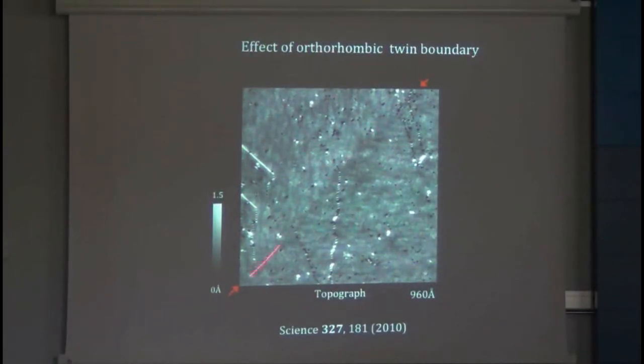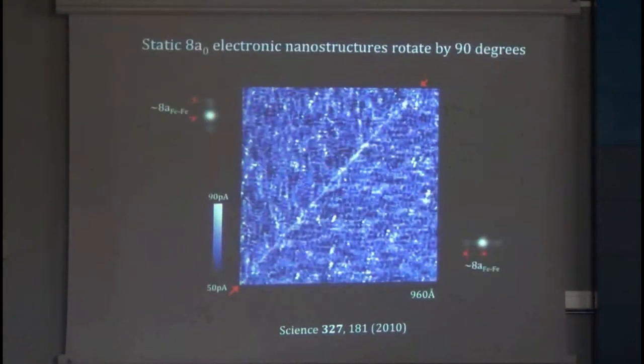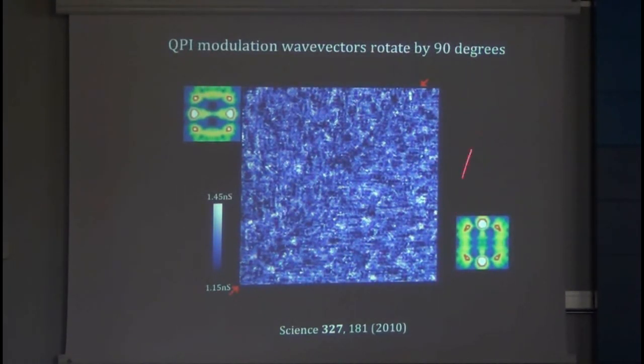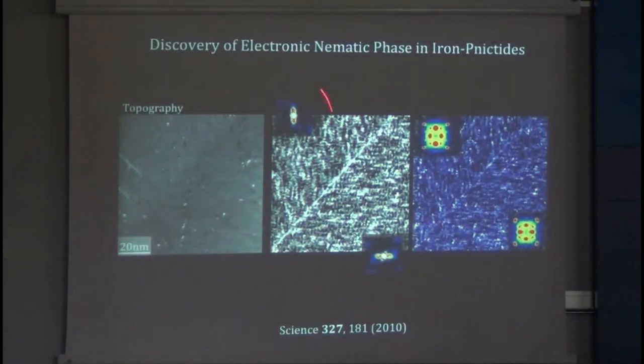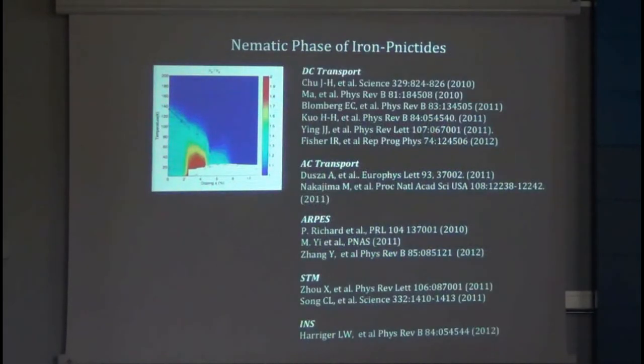So another thing we were able to do in these compounds is find a twin boundary. And that's very important. It allows us to examine the symmetry with more confidence. This is a crystal twin boundary under here. It doesn't look like it in this image, but if I show you the electronic structure images, across that boundary, the nanoscale electronic disorder rotates by 90 degrees, and the dispersive quasiparticle interference signal rotates by 90 degrees across that boundary. Putting all these things together, by the end of 09, we reported that there is an electronic nematic phase in the parent state of the iron superconductors. And now, that doesn't seem like a very interesting or exciting statement, because subsequent to this report, everyone in the world was able to determine that there is a nematic state in the parent state of the iron superconductor. So how come we were lucky enough to get there first?